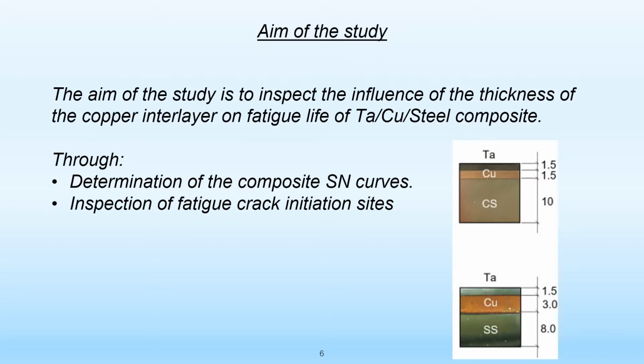The aim of the study is to inspect the influence of the thickness of the copper layer on fatigue life of tantalum, copper, steel explosively welded composite. The methods used were the determination of the composite SN curve and the inspection of fatigue crack sites.